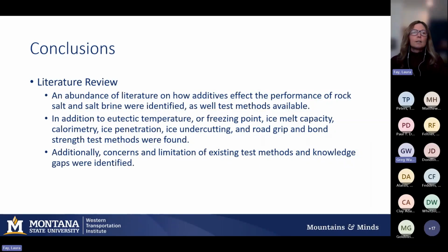So moving forward into the conclusions, the literature review found an abundance of information on how additives affect the performance of rock salt and salt brine. And they were identified and reported in a number of tables. We also identified well-established test methods in most situations that have been used and reported good and reasonable data. In addition to eutectic temperature or measuring of freezing point, ice melting capacity, calorimetry, ice penetration, ice undercutting, and road grip and bond strength are all test methods that have quite a bit of data published on salt with additives.